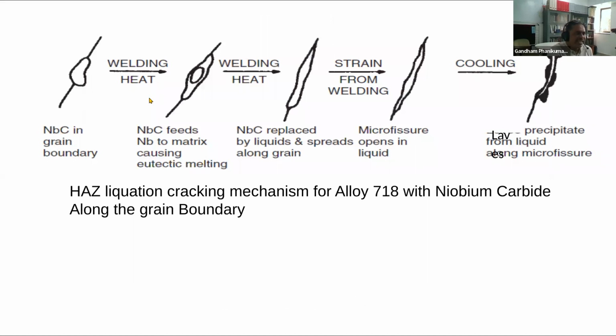So the reheat can actually cause that kind of formation. If you have niobium carbide, for example, this weld heating leads to a liquid formation, forming a crack, and then you will have a problem. Here is where you should relate these things back to what I was talking about in the first hour, namely the segregation of niobium. If you have any segregation, then the possibilities of eutectic formation, or compositions approaching a lower liquidus temperature regime, are very much possible. Therefore we should eliminate such possibilities and avoid serious segregation levels. That's one of the reasons why we have to understand segregations.